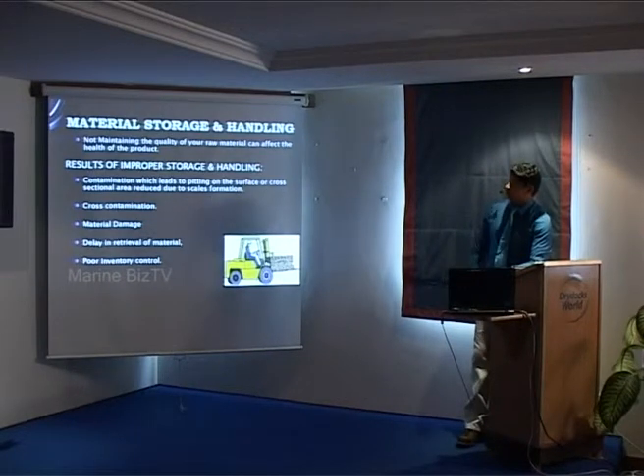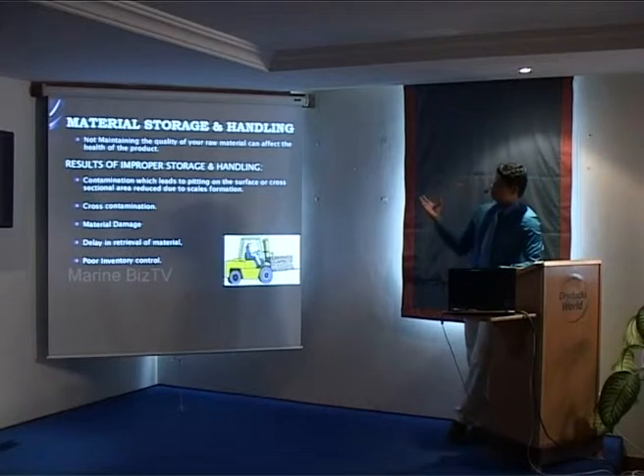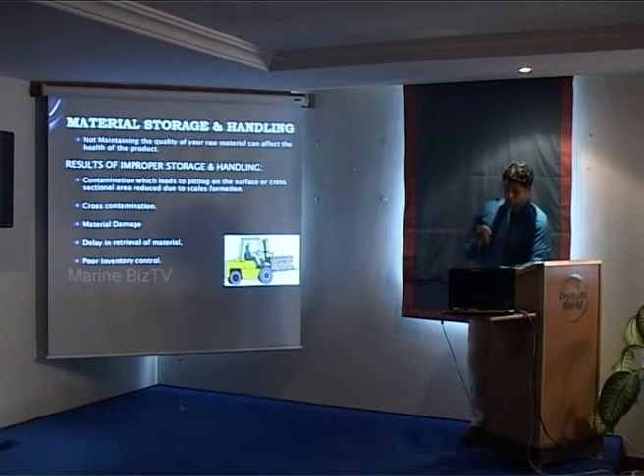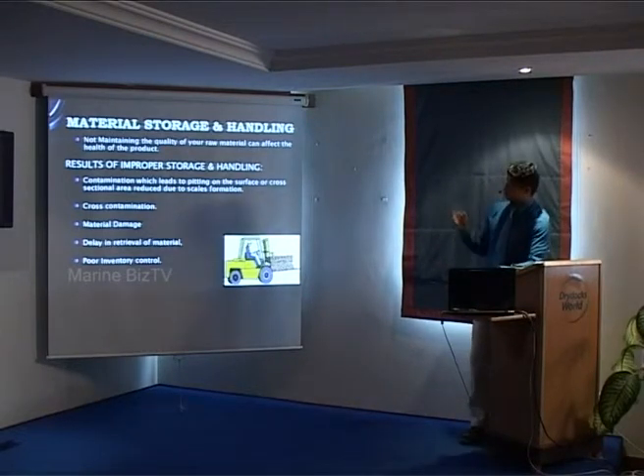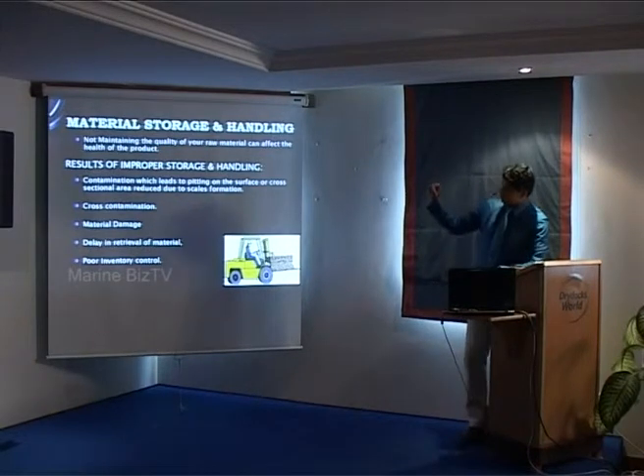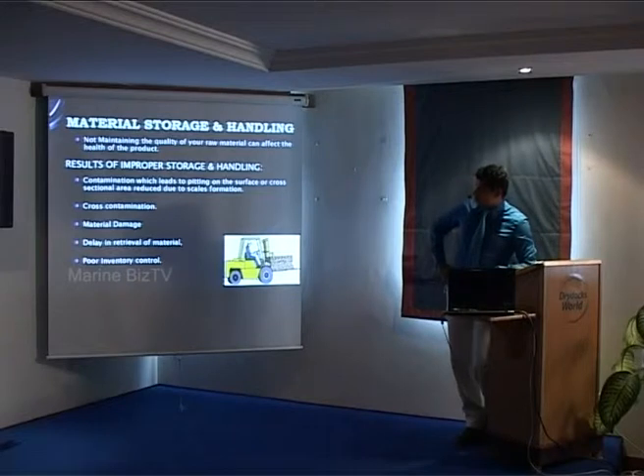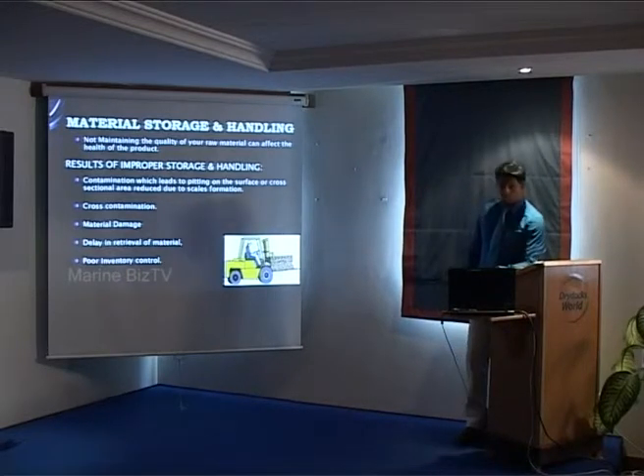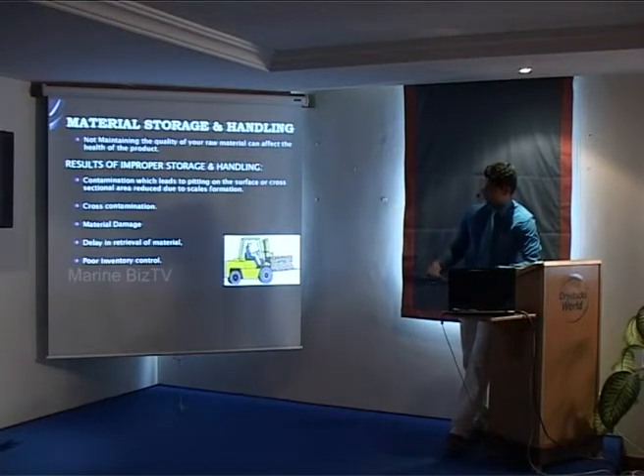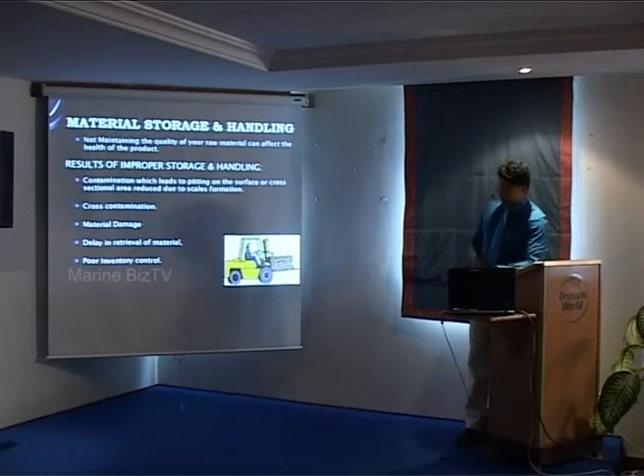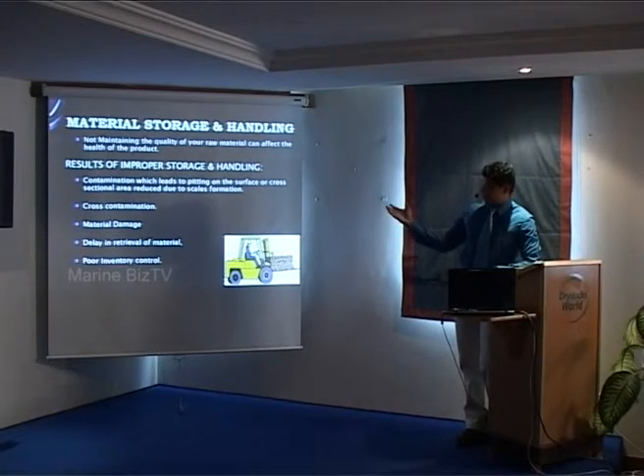The most important aspect for our subcontractors is storage and handling of material. If the material has not been maintained properly, then the product you receive at the end stage definitely won't suit the requirement. If storage is not done properly, contaminations can lead to pitting. You can see scale formation on top of the plate. There can be cross-contamination if stainless steel is mixed with carbon steel, material damage, delay in retrieval, and poor inventory control.